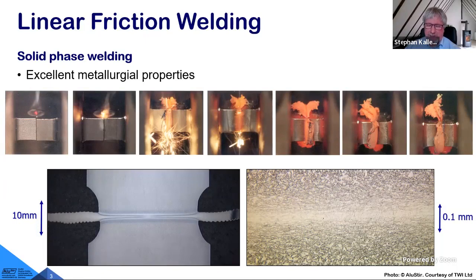The big advantage is, as it is a solid phase welding process, we do not melt the materials. We stay below the melting point of the materials, and we don't even need to apply gas shielding, even in the case of titanium. And as you see, we can get a very nice microstructure. The limitation is there is still a flash or burr on the left and right of the weld that needs to be machined off after welding. It's a process that is very stable and it is used by all aircraft manufacturers. It's a very effective process indeed.